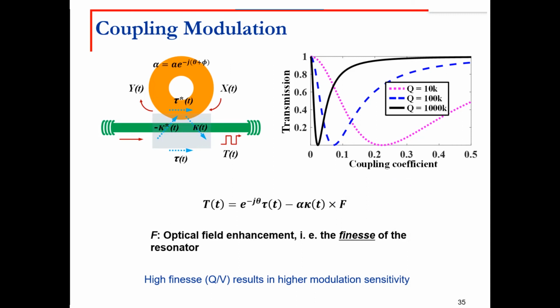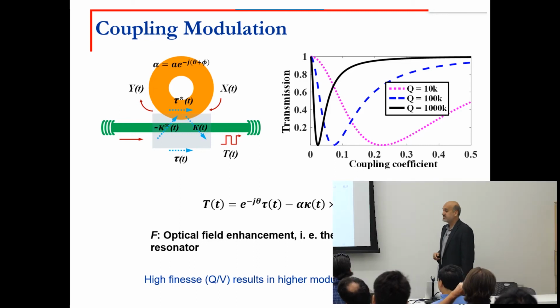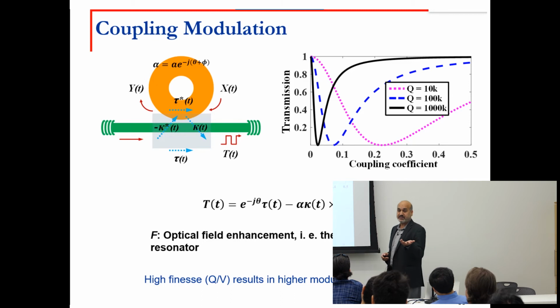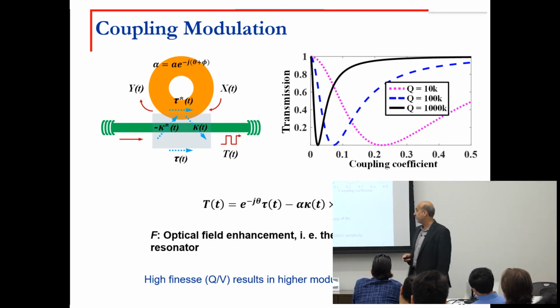So in order to implement this, and I'm not going to get into the details of the formulation, I'm only mentioning that this curve tells us that if the quality factor is higher, then the change that I make in the coupling coefficient is lower to get from maximum to 0 transmission, bit 1 and 0. So higher Qs are preferred. That's why nitride is preferred, because it gives me Qs of tens of millions.